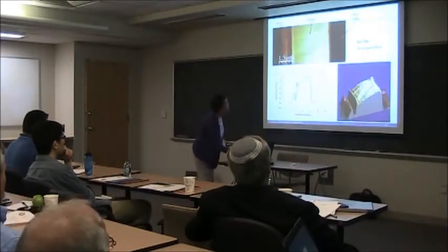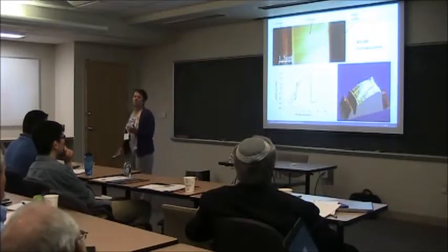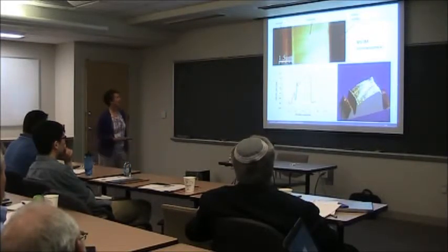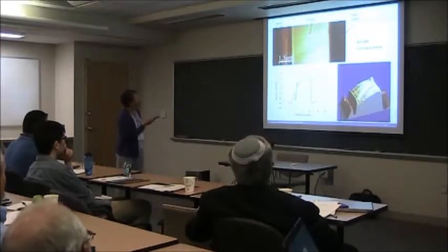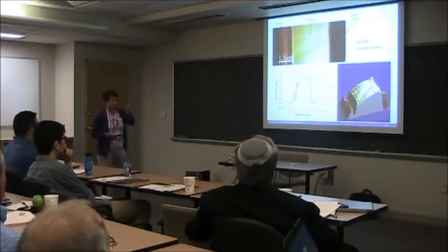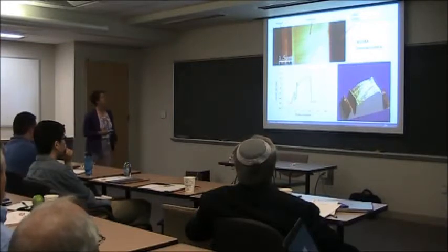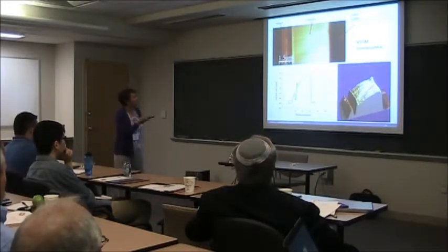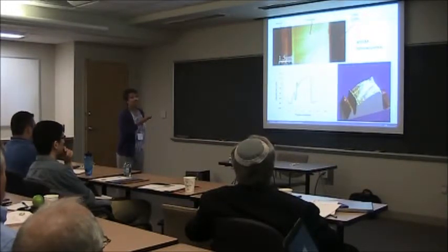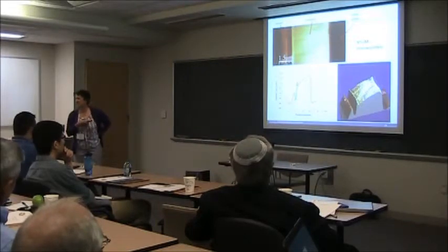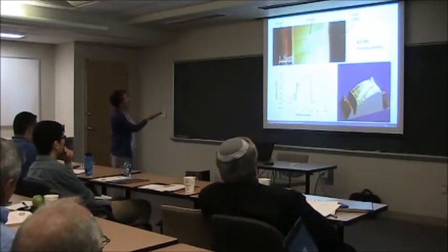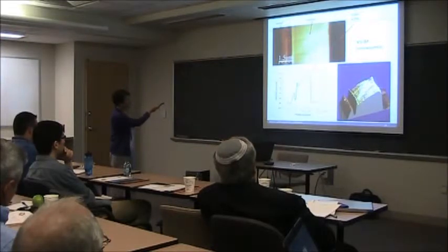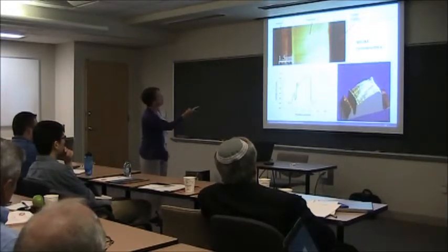Now before we do that, we do all the things you ought to do. We do spectroscopy, we do CL mapping. And this is a PL map. This is data I actually took during my Fulbright stay in Israel. This is an ensemble luminescence PL map where I'm going to do what I told you I never do, which is scan the sample. Okay? So this is a standard map. You see the indium gallium phosphide. This is the region of the junctions, which do not luminesce. There's a lot of carrier recombination. There's a center cell. The third cell would be to the back.